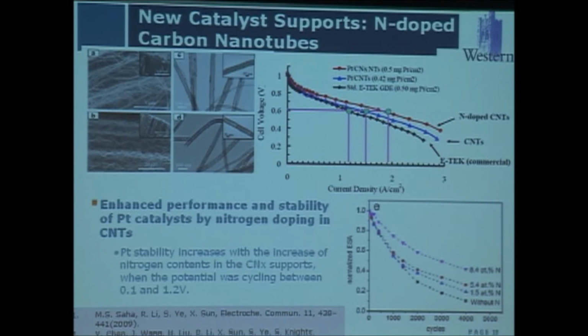Very interesting to us, we also tried to manipulate the nitrogen doping content to improve the durability. You can see that without nitrogen, you get a very quick electrochemical surface area reduction. With 8.4 atomic percent nitrogen doping, you significantly reduce this, but it is still reduced.